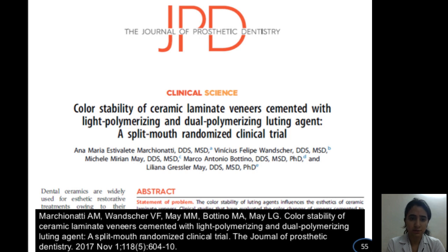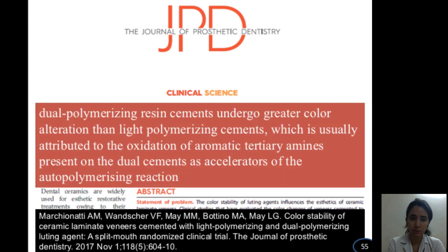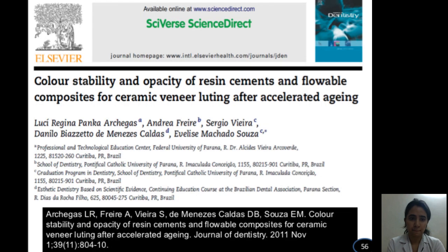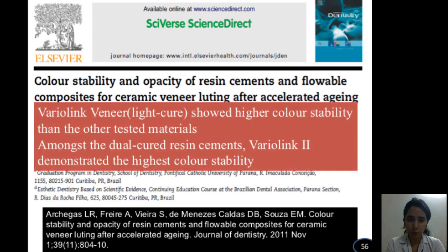First is the color stability of ceramic laminate veneers cemented with light polymerizing and dual polymerizing luting agent, a split mouth randomized controlled trial, in which they concluded that dual polymerizing resin cement undergoes greater color alteration than light polymerizing resin cements. On the color stability and opacity of resin cements and flowable composite for ceramic veneer luting after accelerated aging, it was concluded that Variolink Veneer, which is a light cure cement, showed higher color stability than the other tested materials.